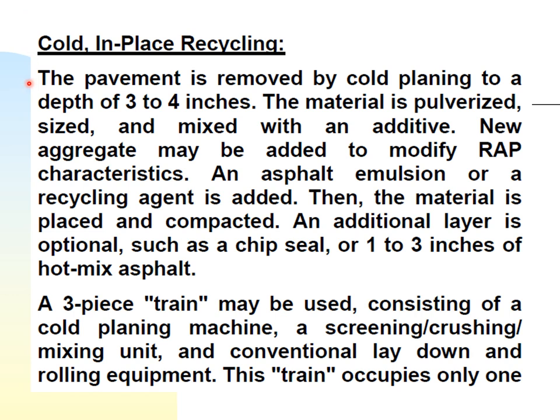The pavement is removed by cold planing to a depth of 3 to 4 inches. The material is pulverized, sized, and mixed with an additive. New aggregate may be added to modify RAP. RAP is reclaimed asphalt pavement. So I will repeat that new aggregate may be added to modify RAP characteristics.